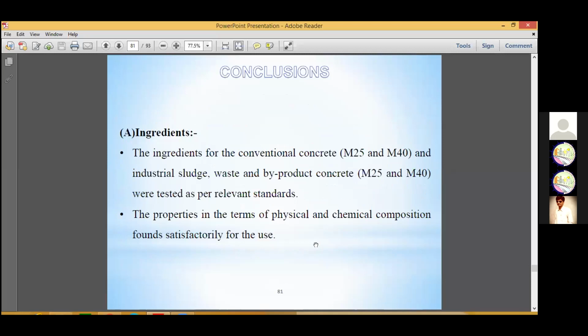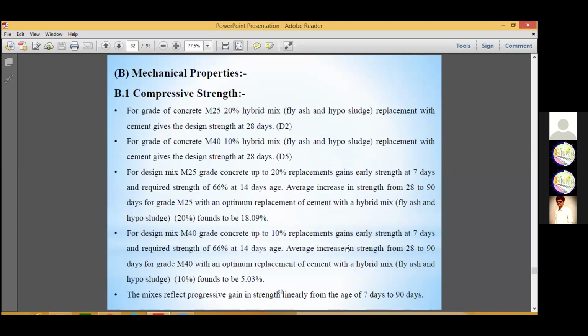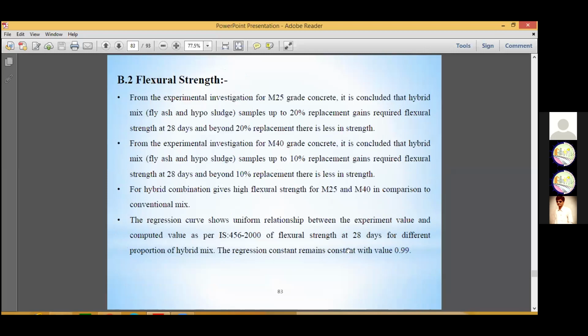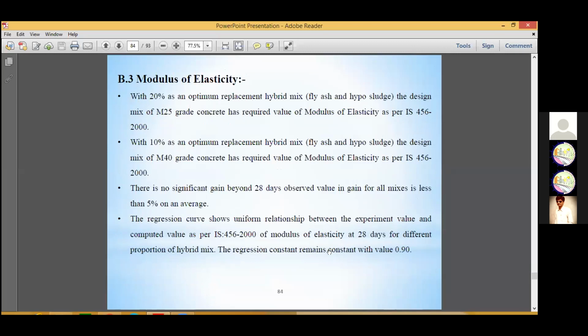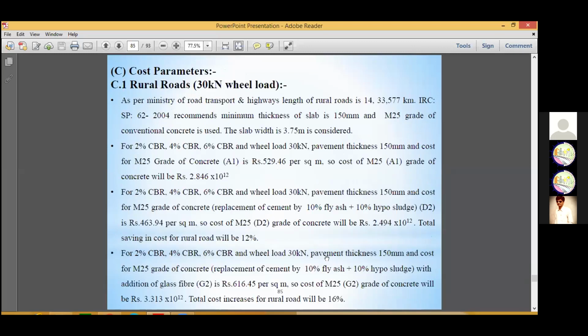Overall, the conclusion we have already discussed in all these slides: the M25 grade and M40 grade with different ingredients, the fly ash and hyposludge, hybrid mix with the addition of glass fiber 0.1%. It is overall beneficial, but the glass fiber cost is somewhat high. So if you add some low cost fibers also, you can refer to low cost sustainable concrete for rural road development and for national highway development.